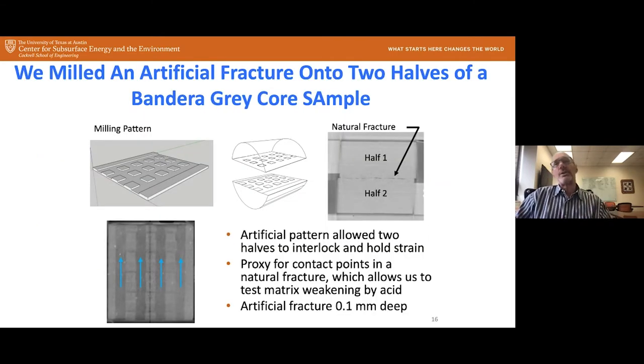So originally we tried to create natural fractures. This is a natural fracture here in the upper right. We have a core. It's about an inch and a half in diameter, maybe an inch to an inch and a half long. We would fracture that and then we would displace it against each other. And I'll show you how we do that in a second. And we try to then look at that, the shear release over time, but we could not get consistent results.